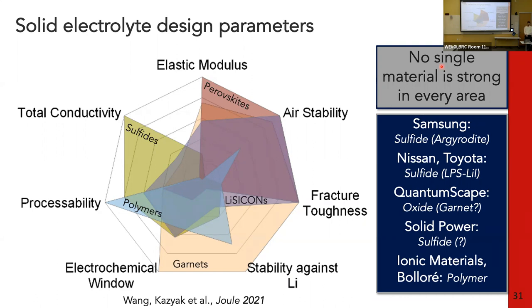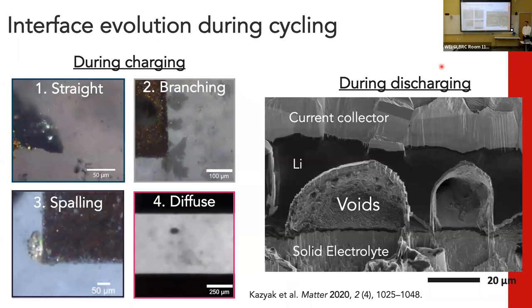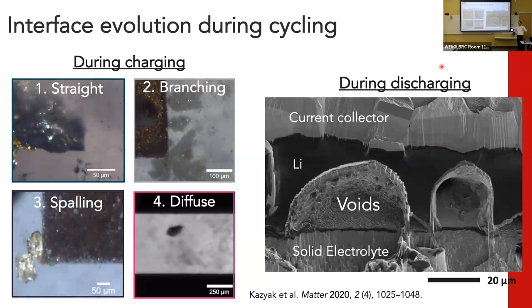The work that I've done in this area, I'm not going to go into detail, but is to understand these challenges at interfaces. And one of the main challenges is when you try to charge too fast. Remember that picture I said the solid was going to make it flat, planar? That doesn't happen in actuality if you charge too fast. The lithium, even though it's soft like chewing gum kind of, because you're plating it out, it can get into the cracks, kind of like a plant growing through concrete, right? It can get into the cracks and then expand, and it can grow even through a very rigid ceramic solid electrolyte, and lithium can propagate from one side to the other and short circuit the cell.